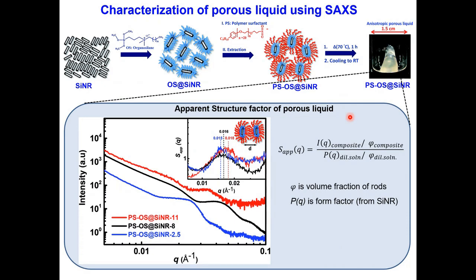Now the interactions come into the picture, or the structure factor comes into the picture. When I say structure factor, I'm talking about two nanoparticles in close proximity to each other. And what is the proximity? It is D, which can be probed by these peaks, and we can fit a very simple equation to find out the average distance between the two nanoparticles. This can be obtained by small angle X-ray scattering. I'm sure this information will not be obtained from any microscopic tool, because for microscopy you'd have to image the nanoparticles, which will be difficult in this particular gel phase. So gels can be very easily characterized using small angle X-ray scattering.